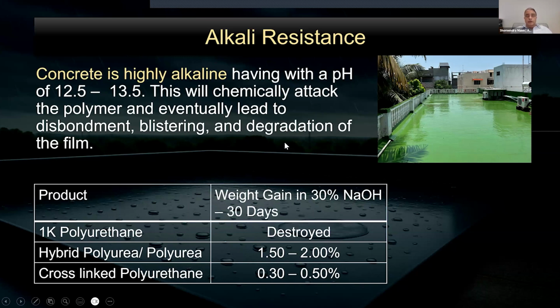So how do we test the alkali resistance? We take the film, we put it in saturated sodium hydroxide for 30 days, and then we see the weight gain. 1K polyurethane, the film is completely destroyed. It shows that it's only very mildly resistant. So this is the surprising part. The hybrid polyurea or the pure polyurea, the weight gain is between 1.5 to 2%, which is kind of okay, but still it is not of the highest order. And you compare it to the cross-linked polyurethane, your weight gain is typically 0.3% in 30 days immersed in saturated sodium hydroxide. So again, very important property, we need to evaluate this.